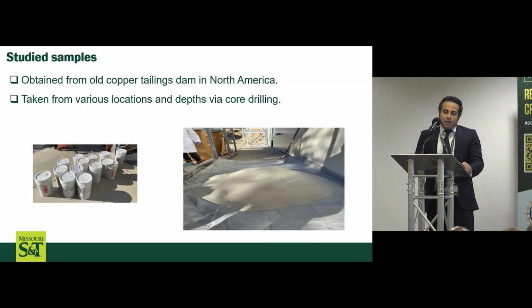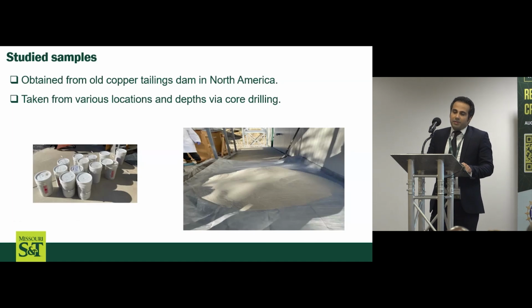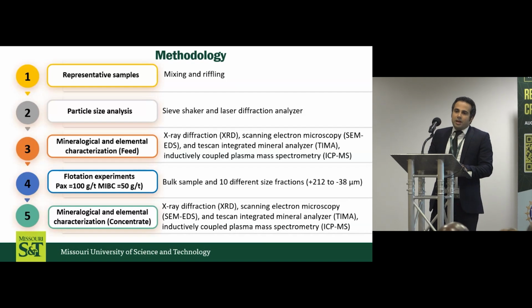In this study, the samples were obtained from an old copper tailing dam in North America, and they were taken from various locations and depths via core drilling. After homogenization and preparation of the samples, particle size analysis was done using a sieve shaker and laser diffraction analysis. Major and mineral phases were identified by XRD scanning, SEM, and TESCAN integrated mineral analyzer. And the chemical composition was determined by ICP-MS analysis.